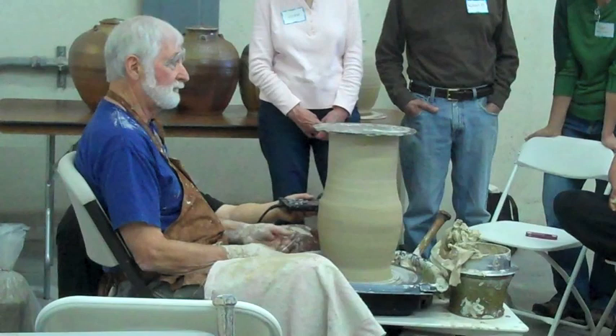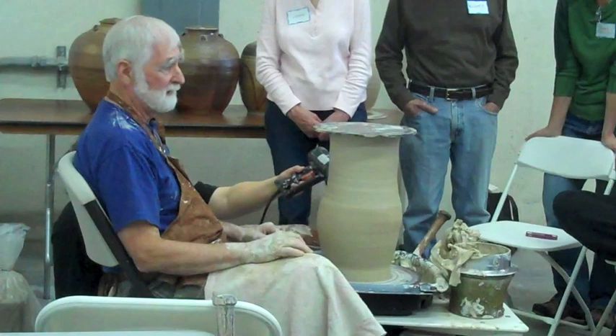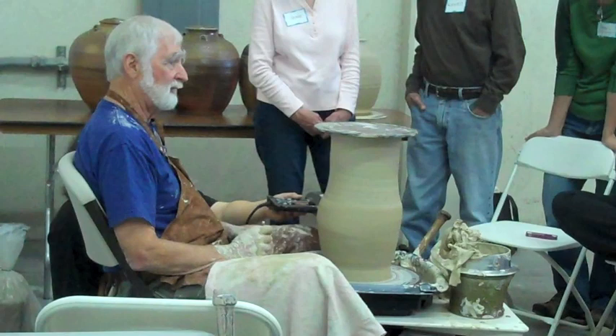Normally, I just pour the glaze over. I turn my pots upside down over this big half barrel I've got, and just walk around it and pour the glazes, always from the bottom, because I like glazes that run, that move, so that they're going to flow, but I know it's going to be thicker where? At the top. I turn it over. That same way when I glaze things, I always dip them rim first. You glaze the inside? Yeah, I glaze the inside, but that's easy.